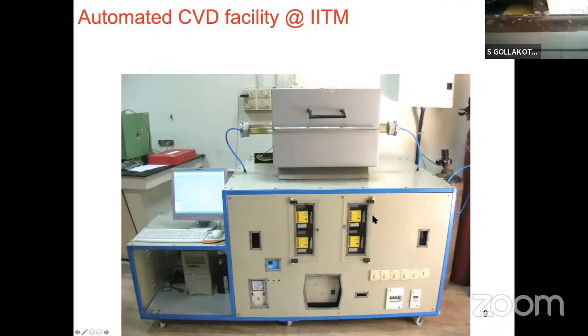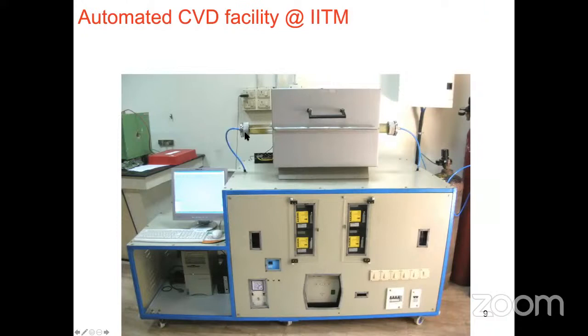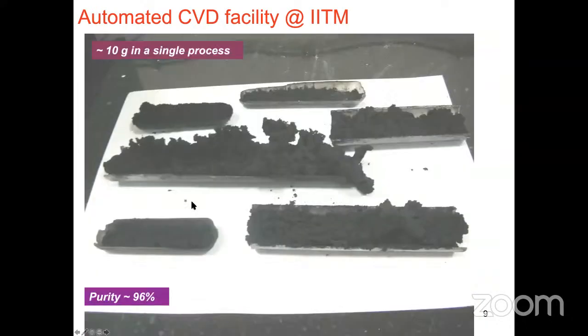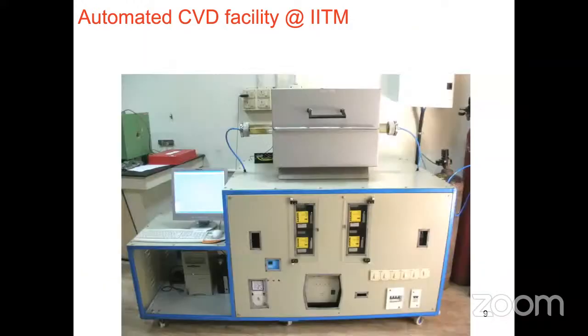Then what we have done is make it completely computerized, with a bigger quartz tube, and instead of flow meters, we have the mass flow controllers, controlled by the computer. So one can get almost 10 grams of these carbon nanotubes in a single shot, which we have done in the lab. Now we wanted to scale it up to almost half a kilogram of carbon nanotubes in a single shot.